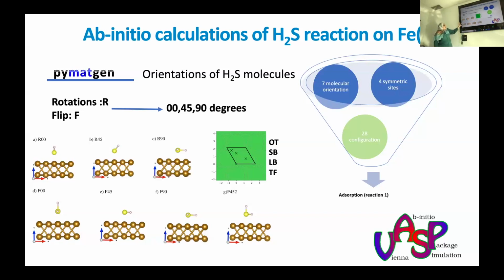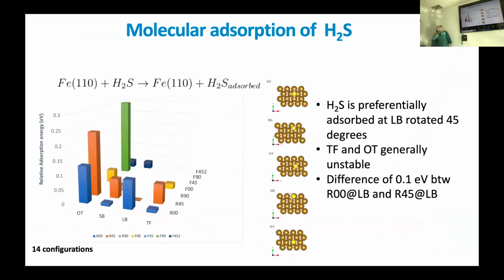So this is not the real thickness of the slab. The thickness of the slab is the same as I showed you. This is just for illustration purposes. So what you can see here is at the end, we found 14 configurations. And then from mapping all different possibilities, we found that H2S actually preferably adsorbs on a long bridge, rotated by 45 degrees. Okay? And we also characterized it. So we looked at all these adsorption sites and how they compete and how this is affecting the sticking probabilities.